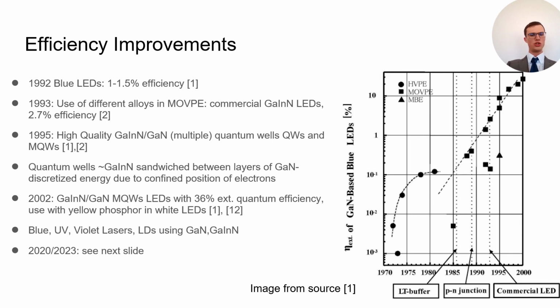In 1995, huge improvements were made using quantum wells and multiple quantum wells. What you can understand in a quantum well is gallium indium nitride sandwiched between layers of gallium nitride. This means you have your actual p-n junction LED sandwiched between neighboring material, which is different but very, very similar. And this means that your electrons in the gallium indium nitride are confined. They are confined, and this leads to a discretized energy, if you remember your uncertainty principle from quantum mechanics 1. And due to this discretized energy, they were able to get LEDs with 36% external quantum efficiency in 2002. This is actually the value we have today. We have not improved on this very much, unfortunately, but it's also crazy. 36% efficiency compared to 1% efficiency. That's 30 times better.